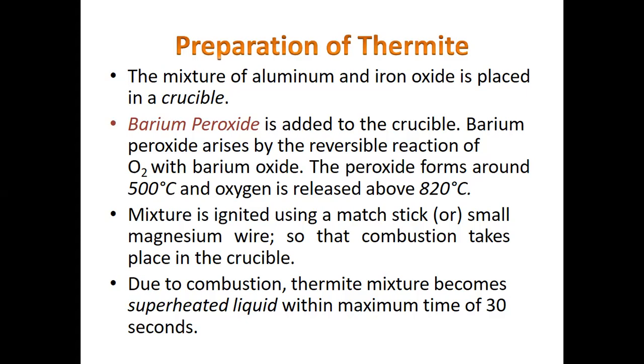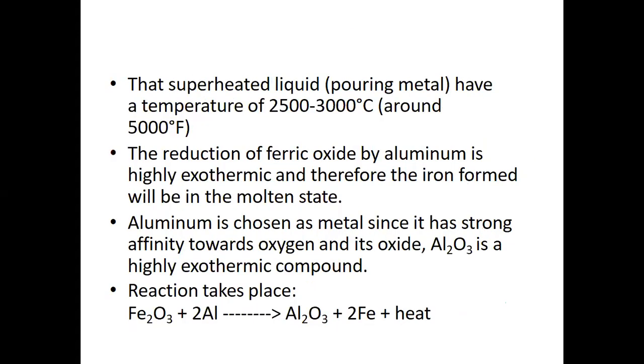Due to combustion, the thermite reaction becomes a superheated liquid within a maximum time of 30 seconds. So that's how quick that combustion is, right? That superheated liquid, which is the pouring metal, has a temperature of around 2500 to 3000 degrees centigrade. If we are looking at Fahrenheit, you have 5000 degrees Fahrenheit. The reduction of ferric oxide by aluminum is highly exothermic, right? And therefore the iron will be in the molten state. So basically we're trying to have that iron, right?